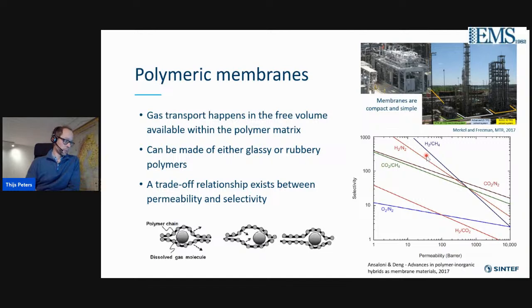And as probably many of you will know, there exists a trade-off relation between permeability and selectivity, shown in this Robeson plot, where typically the low permeable membrane materials show a high selectivity, and the high permeable materials show a lower selectivity. And these lines show the trade-off for the different gas pairs. Of course, in membrane development, all the research is focusing towards getting a membrane material which is highly permeable, but also still shows a decent selectivity.